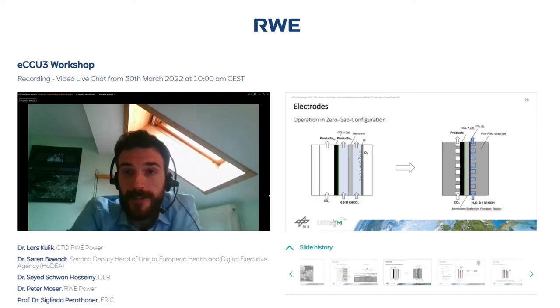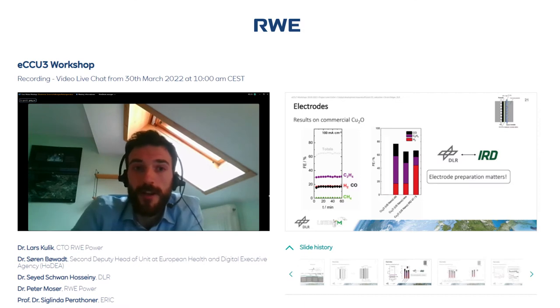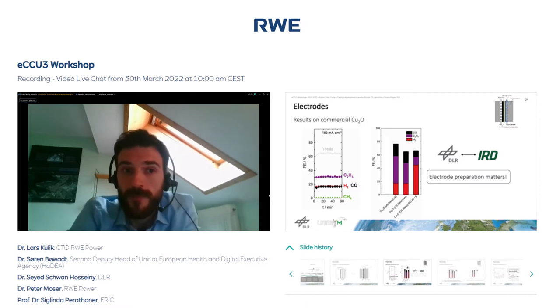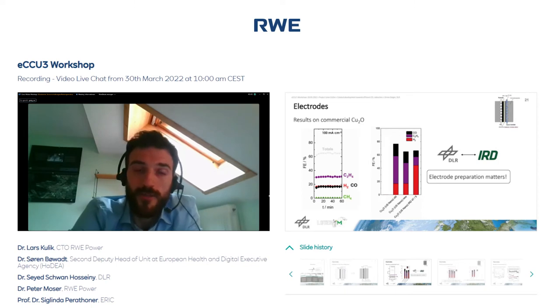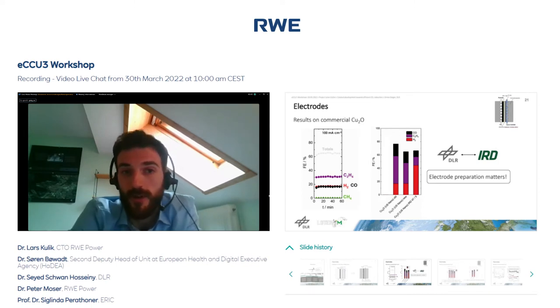And then on slide 20, this is just to indicate that the results I would now show are basically performed in a zero gap cell. And on slide 21, we can see then the first results on the zero gap cell. We needed to transfer the results that we got in this flow through cell to this cell, which was at the beginning difficult, but then we succeeded also this.